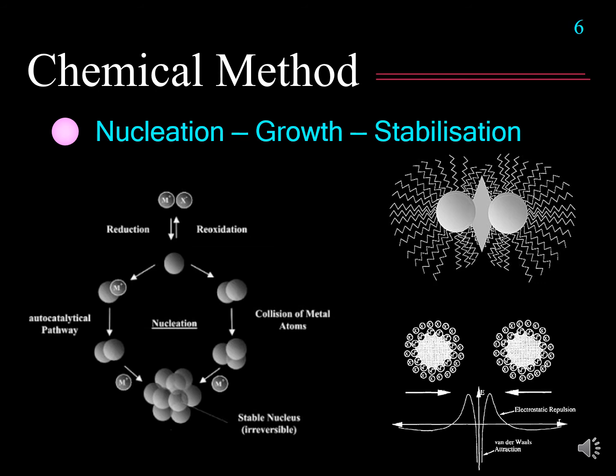Another way we can do is stop it by the electronic field. So if our nanoparticles are absorbed on top with some kind of ion, for example, citrate ion, as I mentioned earlier in the synthesis step, gold nanoparticles synthesized with citrate ion. The citrate ion can have affinity on the surface of the gold nanoparticles. So if an excess amount of the citrate ion is absorbed onto the surface of the gold nanoparticles, at the end the surface of the nanoparticles contains negative charge. So we have negative and negative charge, right? So there is electrostatic repulsion among the nanoparticles, and then we can stop the secondary growth of the nanoparticles by stabilization of the anion, cation, or polymer, right? Using electrostatic or using steric effects.